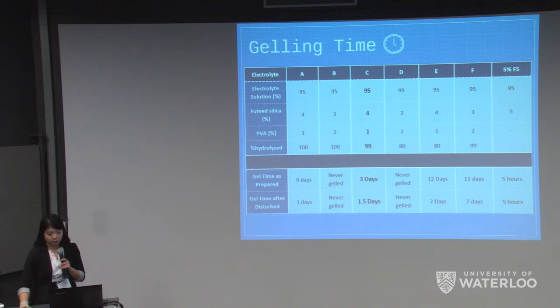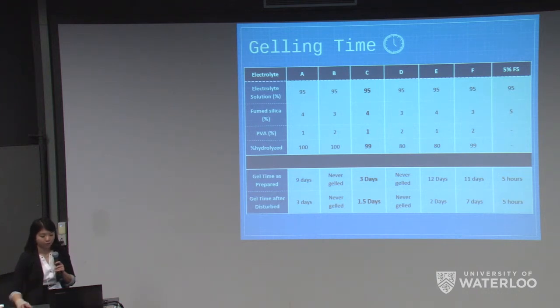So the first gelling time right after mixing is always higher than the consecutive gelling times afterwards. This is because not enough kinetic energy is used to break all of the bonds to allow it to take the same amount of time to gel again as it was in the first gelling time. And focusing on our industry requirement of 4 to 24 hours within the separator, that corresponded to approximately 6 times longer gelling time in the lab.